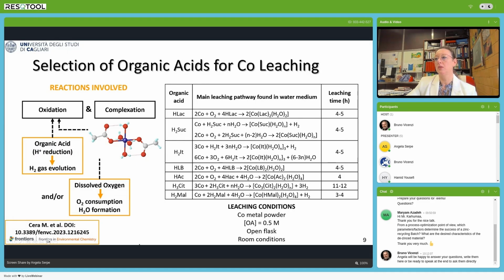This is possible mainly by using this kind of acids with respect to the conventional mineral acids, because organic acids contain the carboxylate moiety that is able to coordinate the metal and then stabilize the metal in the complex form, that is often a species more soluble in water or in other solvents that can be selected for the leaching. So for this kind of leaching we need a double action: the oxidation, which for strong acids is displayed by H+, providing a hydrogen gas evolution, or should be played by other oxidizing agents if the acid is not strong enough for playing this role. The organic part instead may play as a coordination for the metal.